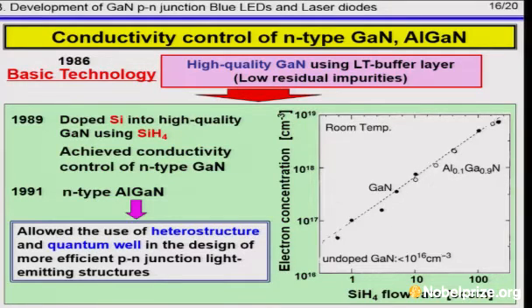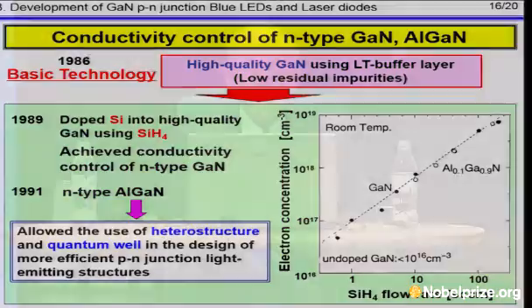In 1989 to 91, we achieved conductivity control of N-type gallium nitride, also N-type aluminum gallium nitride, ranging over about 2 orders of magnitude by silicon doping using silane, while maintaining the high crystal quality by means of a low temperature buffer layer technology.